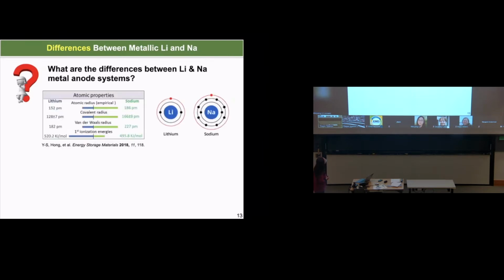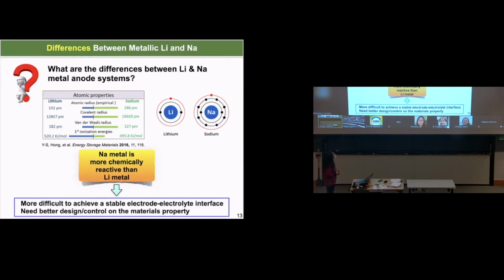If we look at the atomic properties comparison between lithium and sodium, I want to point out that sodium has a much lower first ionization energy, which indicates that sodium metal is more reactive, so it's easier to lose the electron. So the conclusion is that sodium metal is more reactive than lithium metal. If we really want to design a good stable electrolyte interface, if we really want to make sodium metal work, we need better design and control of the material property, because we really need to suppress this high reactivity of sodium metal with the electrode. This is really more challenging compared to using a lithium metal electrode.